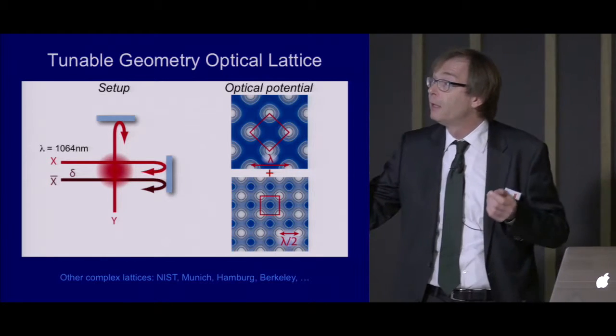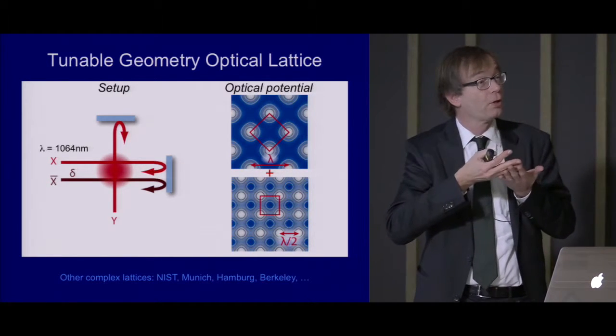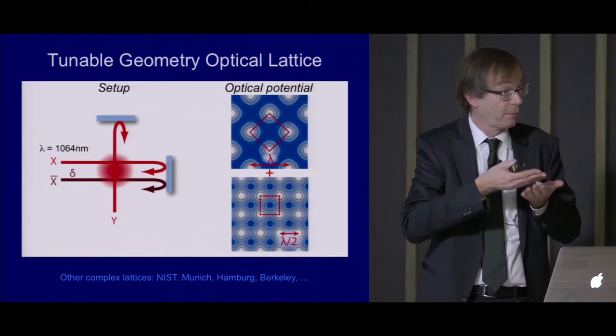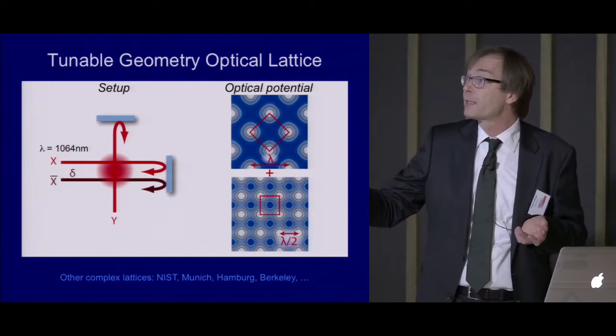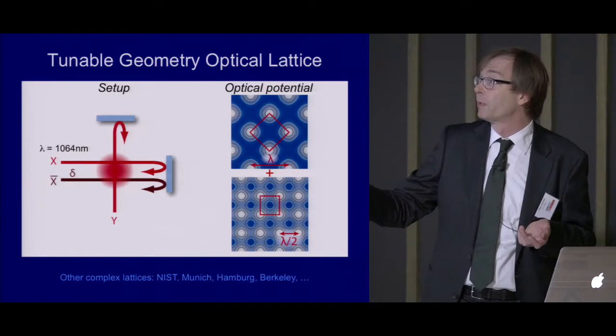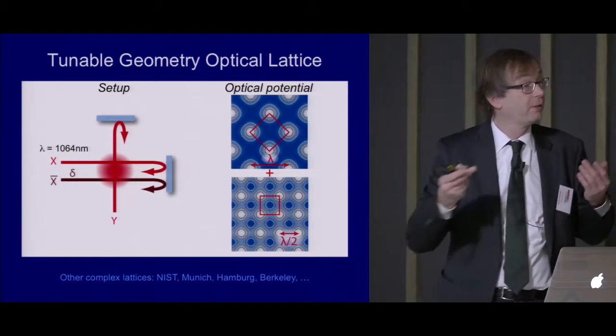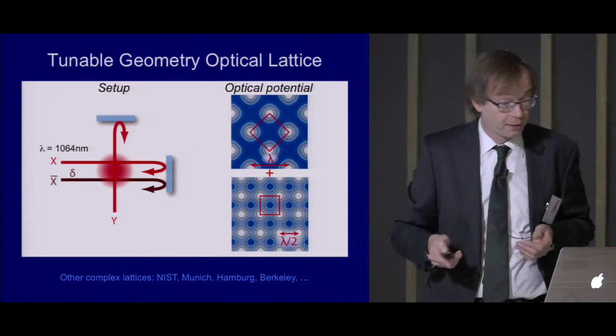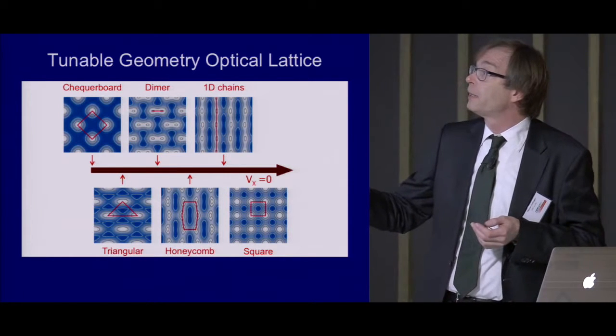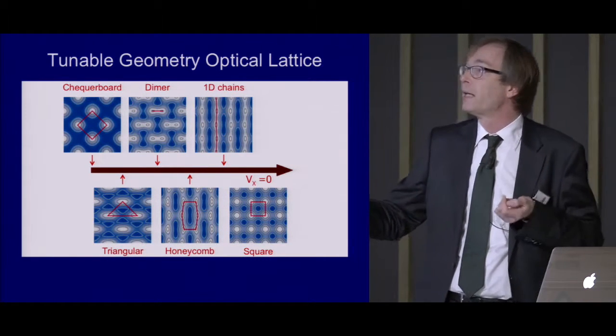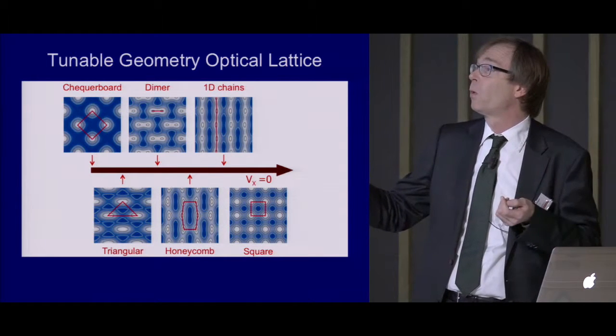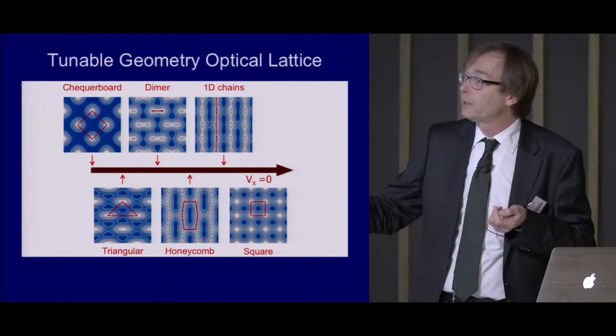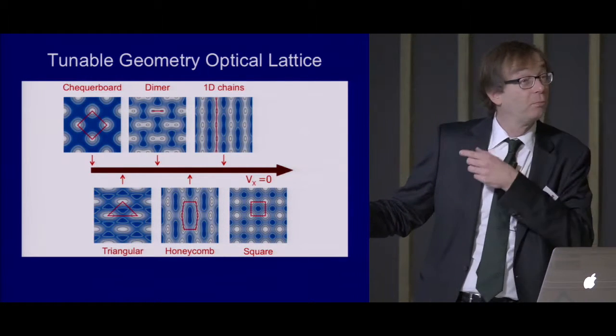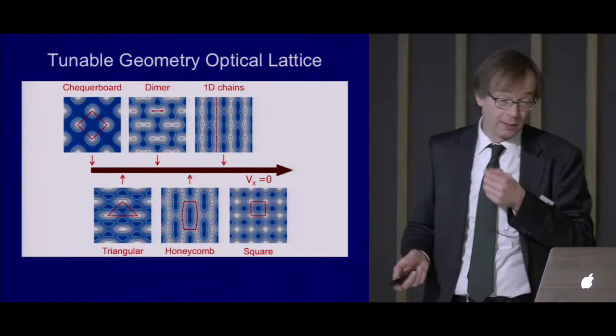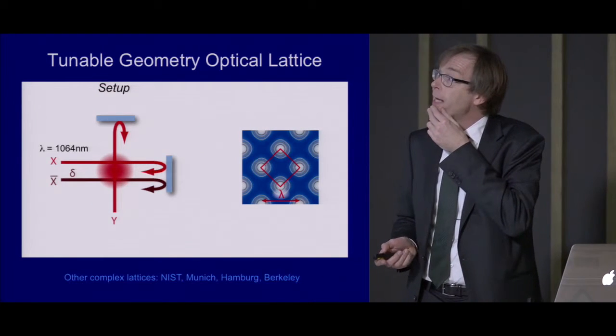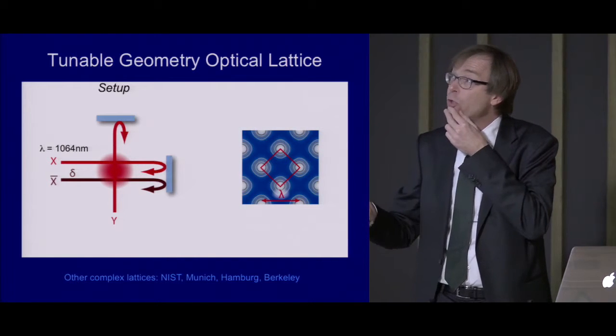And the basic idea of that lattice is that you overlay two interference patterns of two sets of laser beams. So the red beams and here this brown beam. And then you can play with these, overlaying this interference pattern. And what you then realize is that just by changing one intensity, you can create a checkerboard pattern, dimer, 1D chains, triangle lattice, and in particular also a honeycomb lattice, one of these brick type of honeycomb lattice, and a square lattice. And this honeycomb lattice should have Dirac points.